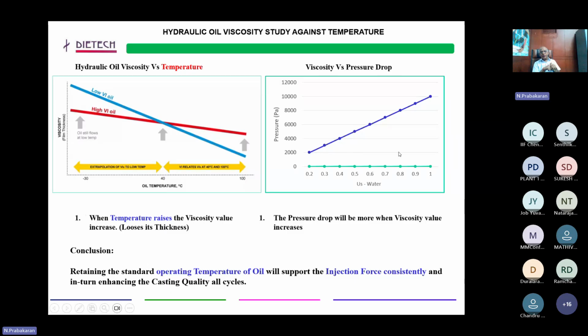If the slope were only around 10 degrees, there would be no much value. But when I look at the pressure drop curve given on the net, nearly 45 degrees means it is equal. Whatever the problem here will be transferred to the pressure drop. If you raise the oil temperature by 10 degrees, your injection consistency will also vary. Certain castings may not have much sensitivity on the injection side, but for most castings, 60 to 70% of them, we are able to maintain the injection force consistency, so the castings produced will be consistent in quality.